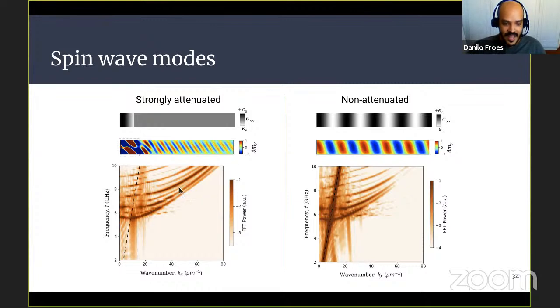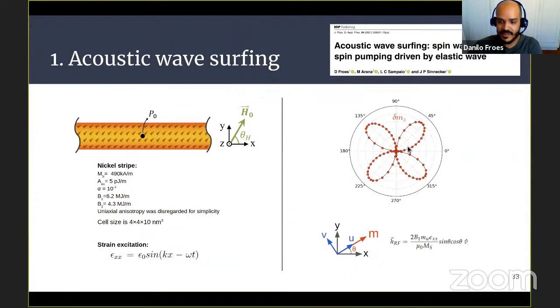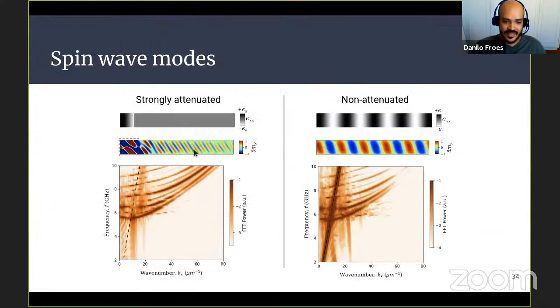So we have these many modes here in the dispersion relations because of the lateral confinement of the stripe. They are very tilted because the magnetization was fixed at 45 degrees for maximum coupling. I didn't say that, but it's important to highlight. We fixed the magnetization direction at 45 degrees. So we have this tilted wavefront and this dispersion.